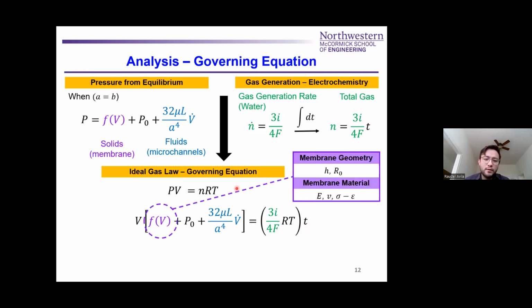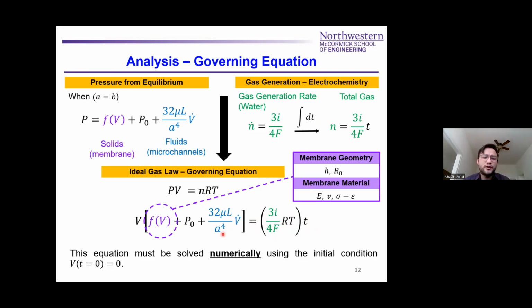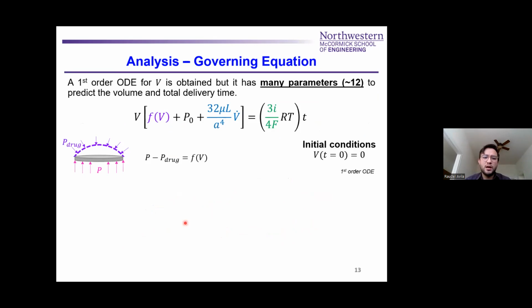So here, just to remind you, the contribution from the function f(V) has the influence of the membrane geometry, but also the membrane material, so the membrane elasticity as well. And this equation, you can solve numerically using the initial condition that at time 0, the volume must be 0. But for the purpose of this analysis, we don't want to solve it numerically, because we're interested in finding an analytical model or a scaling law that can help us understand, if we vary the environment, what's going to be the impact? If we vary the elasticity, what's going to be the impact?